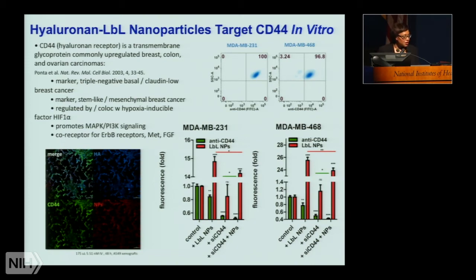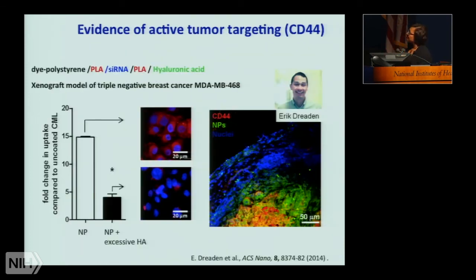But it turned out that because we were focused on high-grade ovarian cancer, triple-negative breast cancer, and some of the advanced lung cancers, all of those cancers overexpress the CD44 receptor, which happens to be the hyaluronan receptor. As it turns out, that high affinity for CD44 allowed us to use just the hyaluronic acid outer layer as the targeting molecule. So once again, we did a series of experiments to show that we're getting targeting based on CD44 interactions with hyaluronic acid. And I'm describing the work of my postdoc, Erik Dreaden.